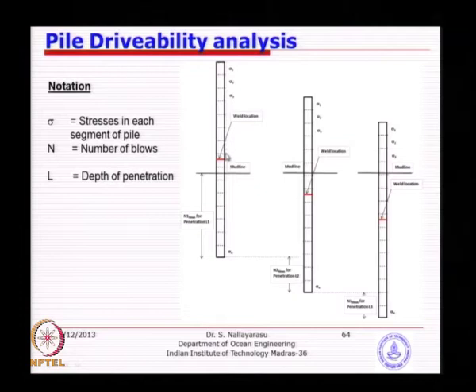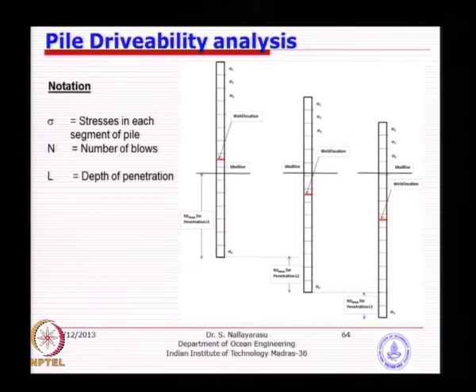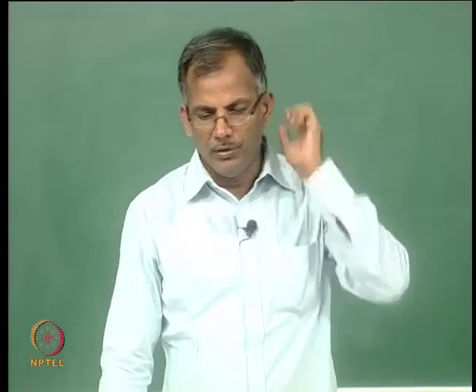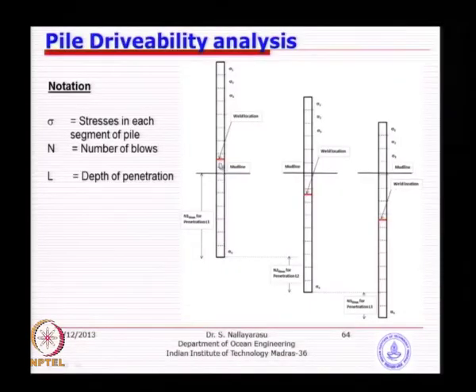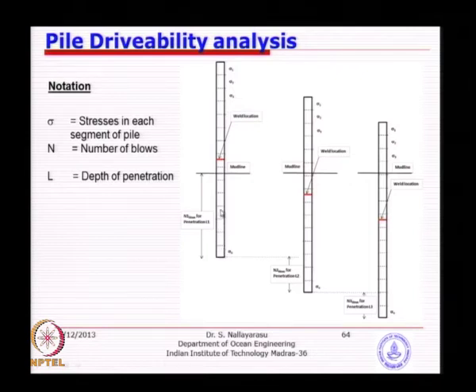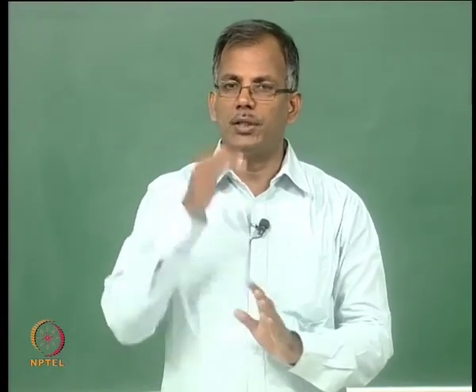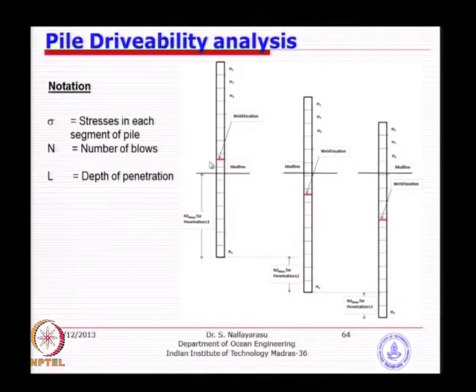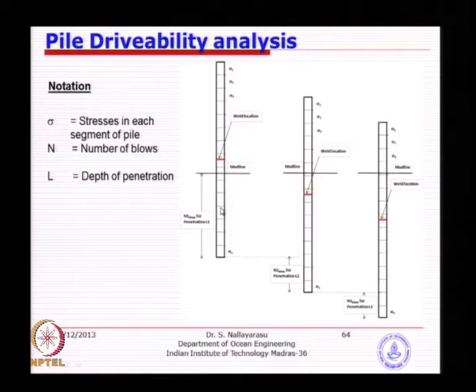You will also have fatigue along the longitudinal seams, but not very critical because the stress concentration will be lower. The most critical one is the connection between two pieces of pile segments inserted into the soil. The pile has been divided into several sub-segments along the length, and you will be monitoring the stresses at each of these locations. From the pile driving analysis, you will find out the stresses at various levels during driving.